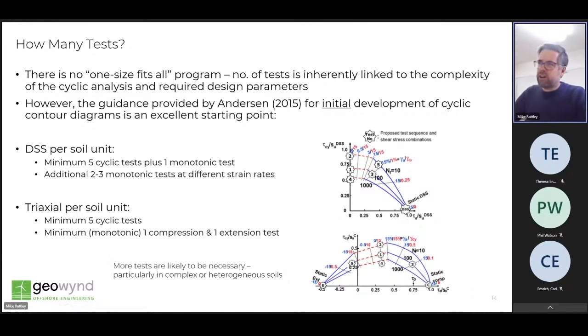There's no good definitive answer to how many cyclic tests are required for a given design project. This is related to the requirements and complexity of the cyclic analysis to be performed. However, there is some quite useful guidance in Knut Andersen's 2015 keynote on developing test programs for definition of cyclic contour diagrams, which is a common application of the cyclic data. And this is shown on this slide and essentially is a good starting point for test programs. The recommendation is for a minimum of 5 cyclic tests per soil unit, with at least one monotonic reference test, as Carl mentioned, to provide an SU value to normalize the cyclic response.